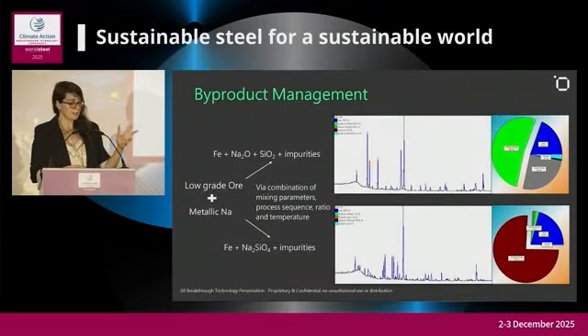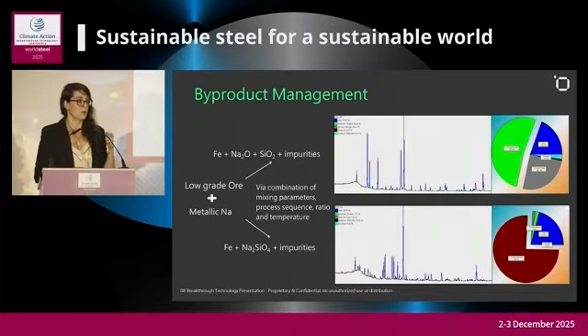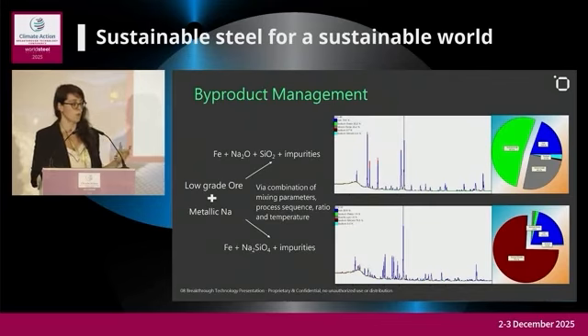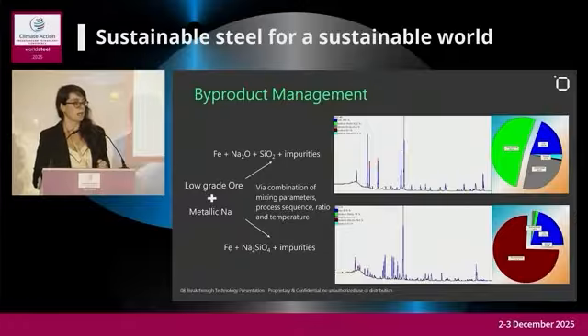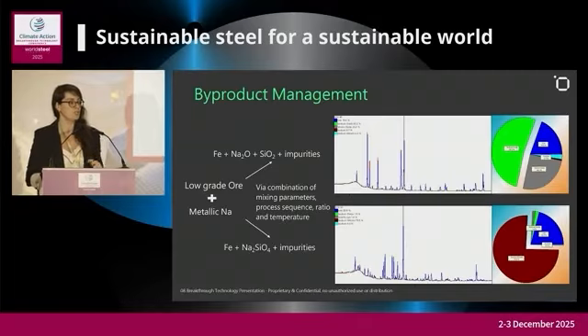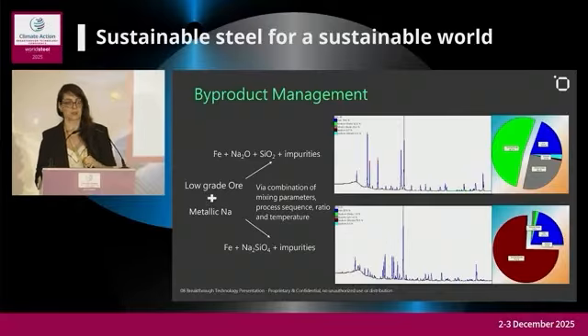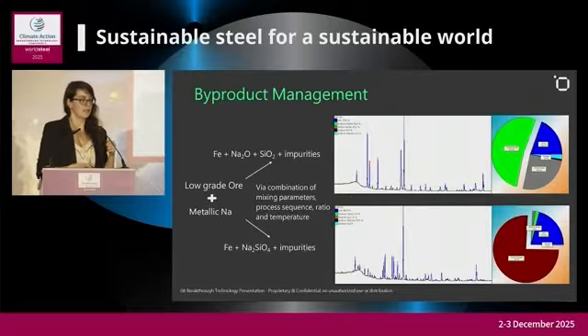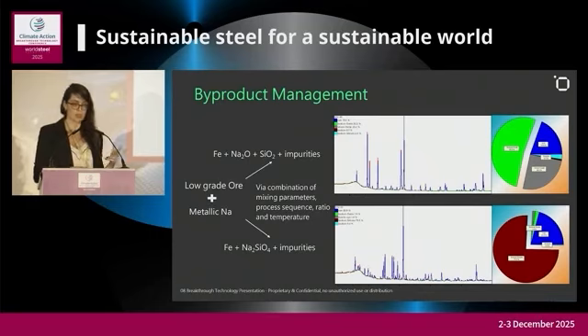So in this slide, you can see our ability to manage the byproduct. You can see here 2 examples of XRD from the same low-grade ore, and by monitoring different process parameters, whether it's the mixing, the ratio, or the temperature, we've managed to control the outcome after the reduction. Meaning we can control in the process if we want to reach silica at the end or sodium silicate in the end.